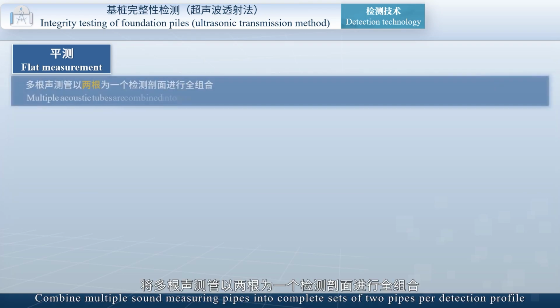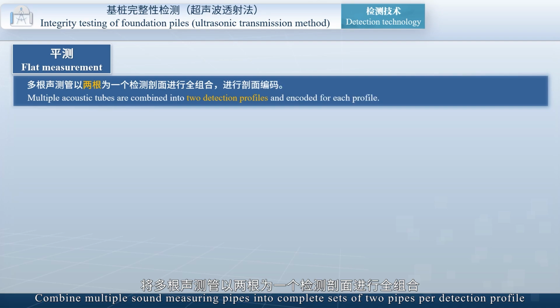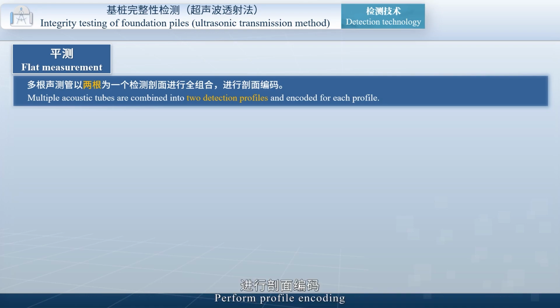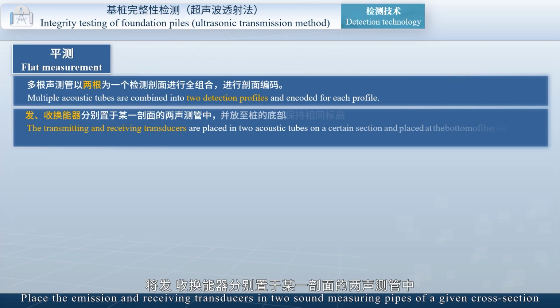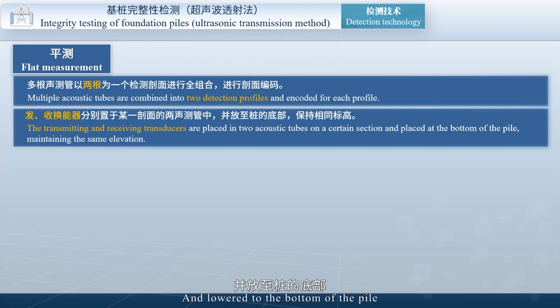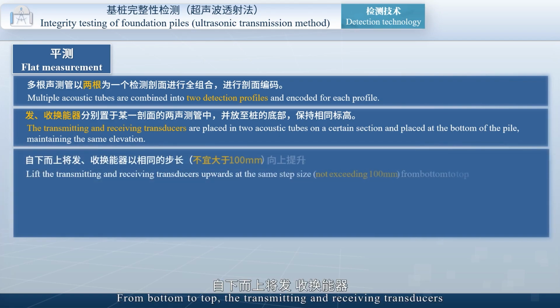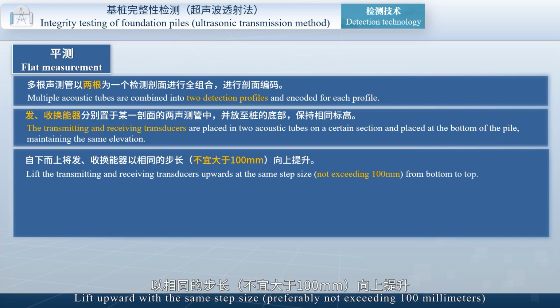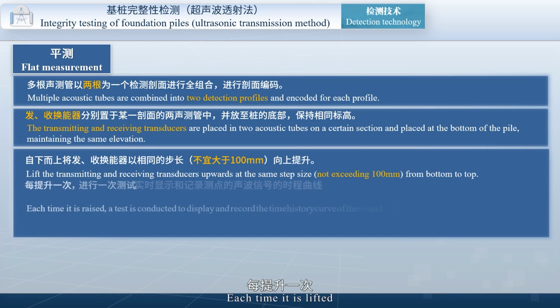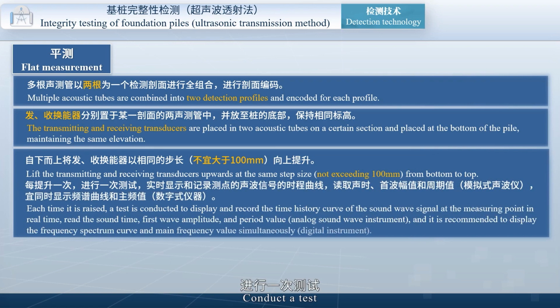Step 1. Combine multiple sound measuring pipes into complete sets of 2 pipes per detection profile. Perform profile encoding. Step 2. Place the emission and receiving transducers in two sound measuring pipes of a given cross-section, and lower them to the bottom of the pile. Maintain the same elevation. Step 3. From bottom to top, lift the transmitting and receiving transducers upward with the same step size, preferably not exceeding 100 millimeters. Each time it is lifted, conduct a test.